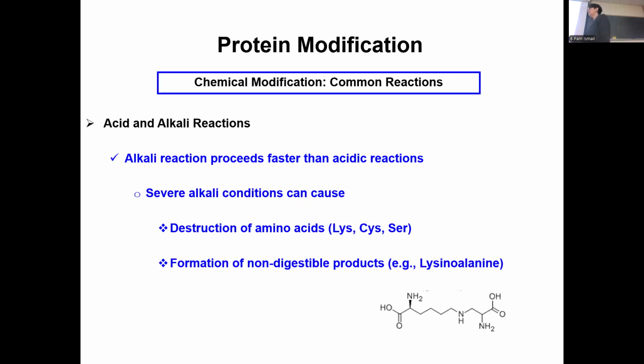However, high alkalinity, that's why when we try to extract proteins, especially plant proteins, we want to figure out ways to extract them at lower pH. Because high alkalinity is not good for the protein. It can destroy essential amino acids, such as lysine. It can also form non-digestible products like lysinoalanine. And it also causes oxidation. So if you have components that might get oxidized at high alkalinity, you get oxidation, off flavor, off color, protein polymerizing. So it's not a good thing that happens.